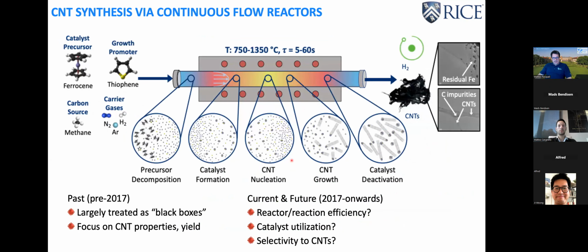So how does this work? Right now, these are flow-through reactors. They're catalytic reactors or catalysts. Precursors are injected in the reactors, or they are placed on catalyst supports, as Matteo Carniello does. And the typical reaction temperatures are, let's say, in the ballpark of about 1000 C, a little lower for supported catalyst, a little higher for what's called floating catalyst. And then one has control of all the processes of catalyst, precursors decomposition, formation of a catalyst, nucleation of the nanotubes, all the way to the growth.